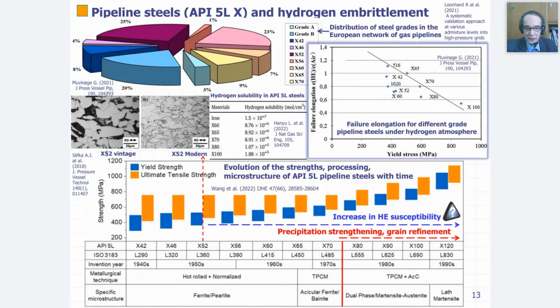As you can see in the down middle section, we have the evolution of the strength and processing microstructure of various pipeline steels with time, including low grade, older pipeline steels like X42, X46, X52, up to the very modern high strength steel for pipelines like X80, X90 and others. In the pie diagram on the upper left part, you can see that in the European Union various grades of pipeline steel are used in percentage, but almost all are up to X70. So the newest ones are still not in use in Europe.